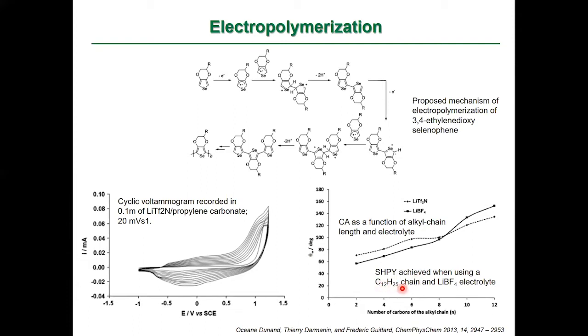C12H25 chain and a LiBF4 electrolyte, the superhydrophobicity was achieved. That was a better condition for superhydrophobicity, and so it depends upon the condition, and as we already know, it depends upon the surface morphology of the deposit, and the energy of the deposit,